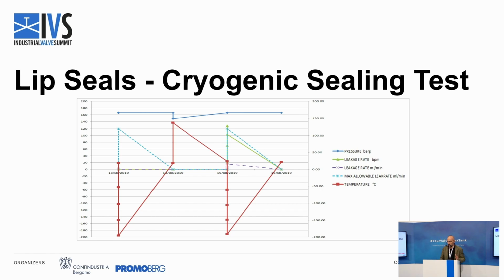So the conditions that the seals will face will change. We could have low pressure. We can go from minus 162 to ambient temperature, and then we can go down again to minus 162. So we need to be sure that our seals and our material that we choose can actually go back to cryogenic conditions after the heating, and that they can achieve the same level of sealing. So this test basically recreates this kind of condition.